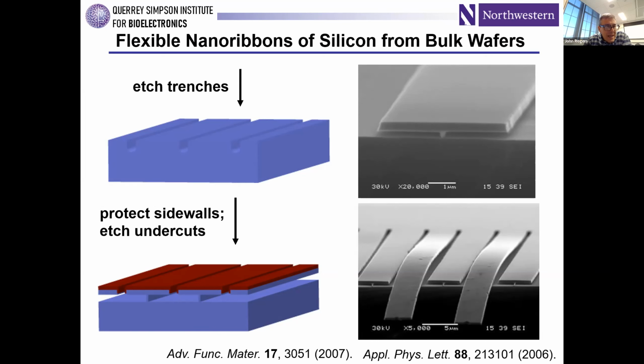But all organic semiconductors are relatively low performance electronic materials compared to silicon, for example. And it just so happened that we were very interested in nanoscale forms of silicon in the context of the work that we were doing in flexible electronics. And so we developed various synthetic and top-down approaches to nanostructured elements of device-grade silicon, as illustrated here in the form of these silicon nanoribbons developed by etching the near-surface regions of device-grade silicon wafers. And those nanostructures were interesting to us for their mechanical properties, and you could integrate those ribbons and membranes and wires and so on with flexible plastic substrates to build high performance flexible electronics.